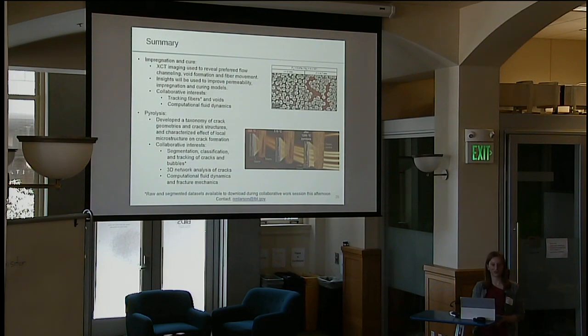So you're referring to the registration of the data sets in 3D? That was actually a bit challenging. I tried to do an automatic registration, but because the fibers are moving and voids are forming, it really wasn't working very well. So any tips on how to make it automatic would be great. But what I ended up doing was finding points in the 3D volumes that actually correlated because I knew they weren't moving. For example, these could be fibers that are embedded in the glass tube along the edge. Those tend to not move.